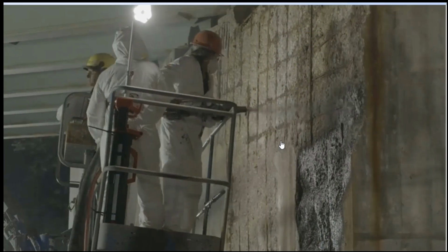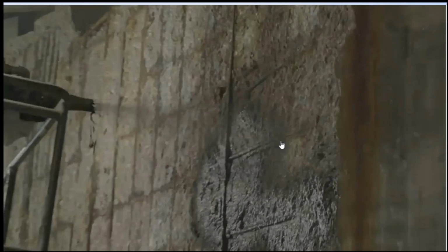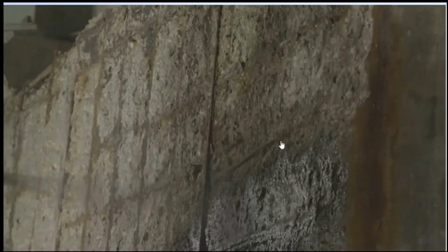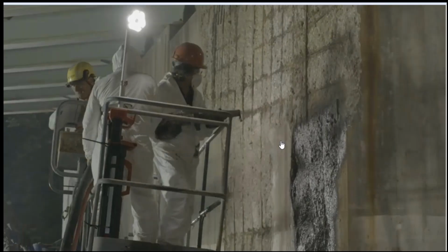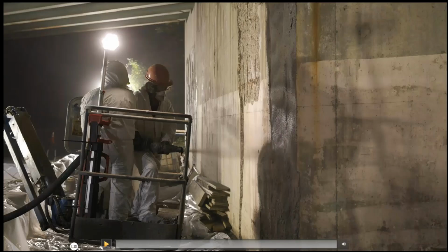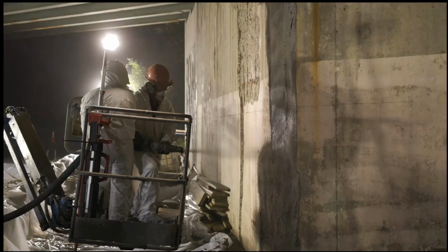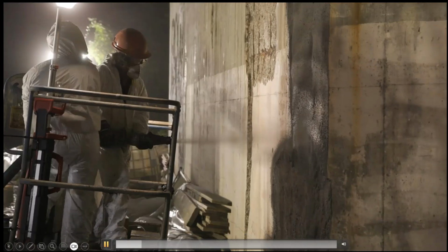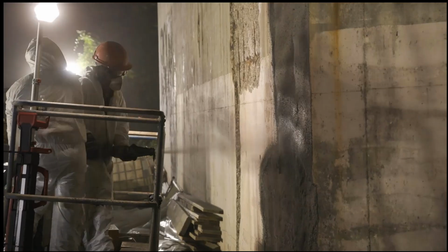So as you can see, this is after applying it. In some places, we had more than 1 inch. Actually, we went back and forth, several layers. Again, when you apply this spray, you go from one end to another. The larger the area is, the more chance the material you applied to the first region has to dry up before you come back. So if you apply layer by layer, you have to let the first layer dry up a little bit, then you go to the second layer. So this is another area. As you can see, there is really no elastic rebound.